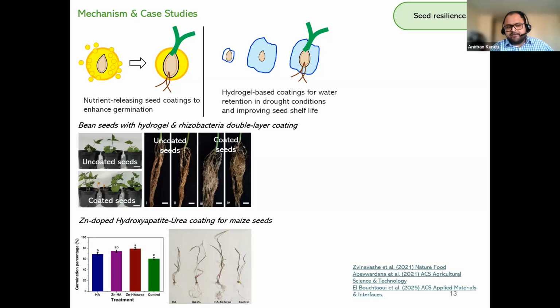Now, of course, in this study, often you'll not get enough effectiveness. Like you see here, the zinc hydroxyapatite has almost the same effectiveness as the coating itself. But again, this would have a much greater impact in areas or regions that are facing climate related risks, or if you had to preserve the seed for a longer period of time.